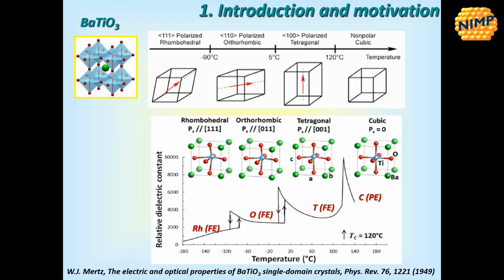I am going directly into the introductory part, the motivation of our study. Barium titanate, such an old ferroelectric material, discovered about 70 years ago, presents a few structural polymorphs in different ranges of temperature. Assigned to these polymorphs, we have a polarization that changes direction in rhombohedral, orthorhombic, and tetragonal states below the Curie temperature, and polarization disappears completely in the ferro-paraelectric transition when the system turns into a nonpolar cubic state.